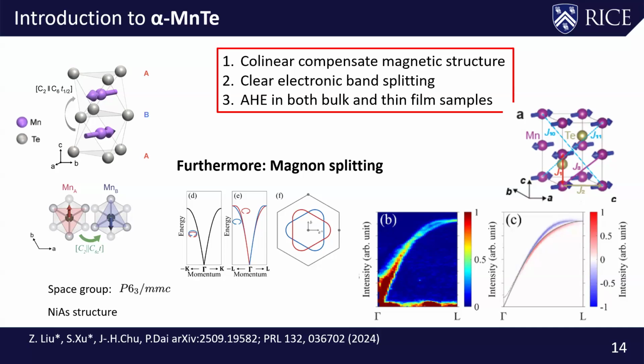But in fact, you actually do see the splitting, and that, in my opinion, is extremely strong evidence that the local environment actually matters for your spin wave band splitting, which is a key indication that the system is generally an altermagnet.